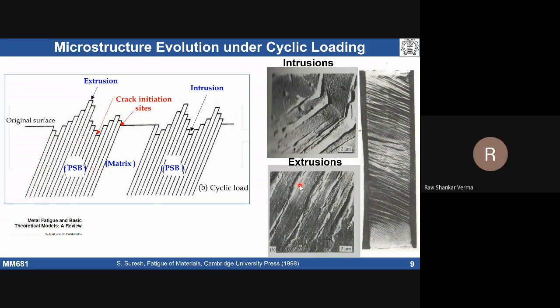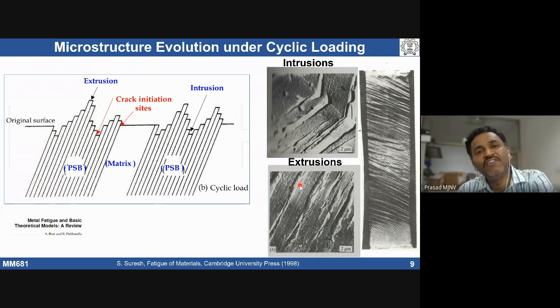So this will be a surface phenomenon only, or in between also? Fatigue cracks always get initiated at the surface. Surface preparation is very much important. So fatigue is a surface phenomenon. The surface is the most dangerous spot for the crack to initiate under cyclic loading conditions.